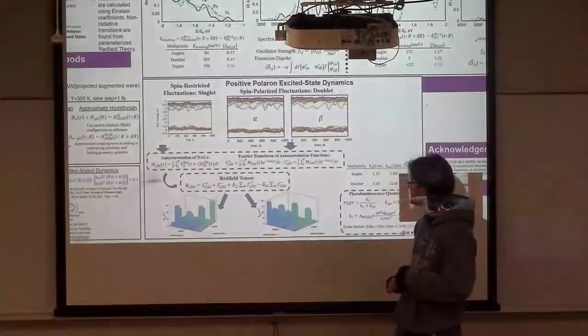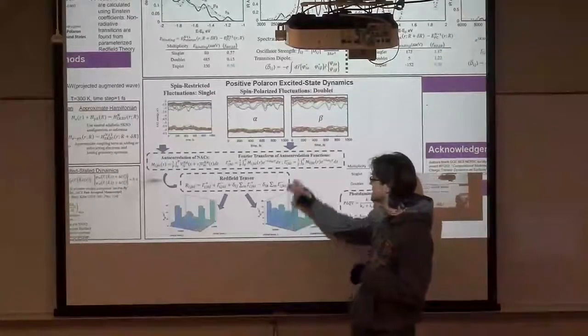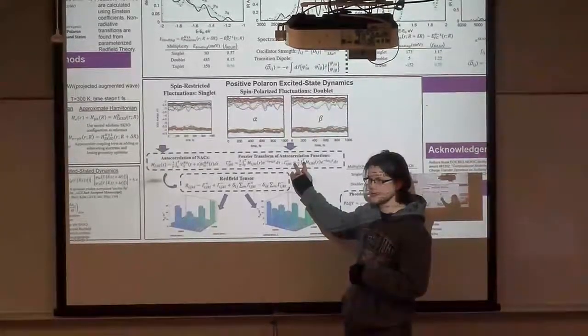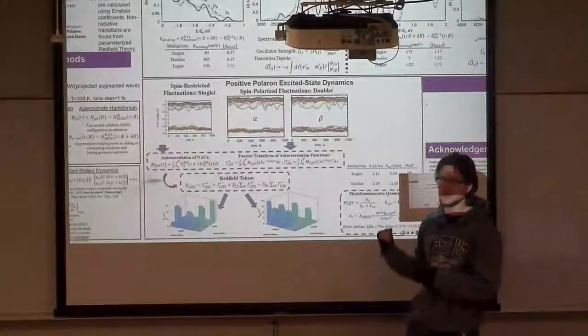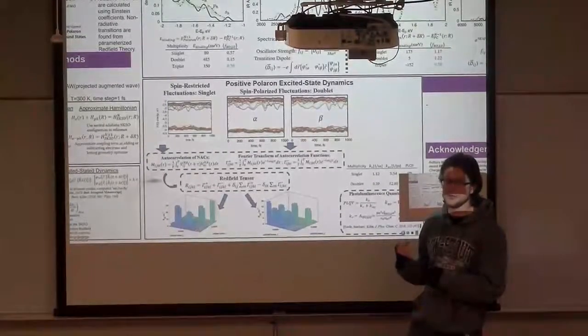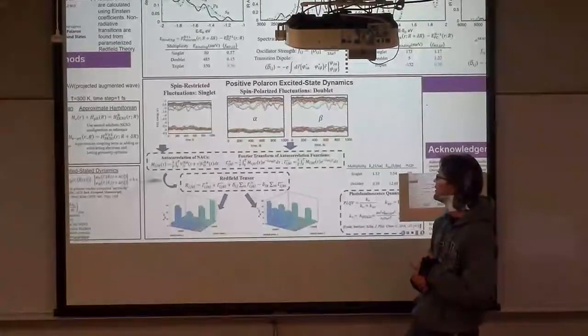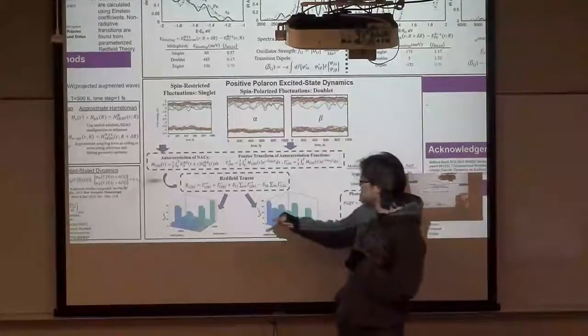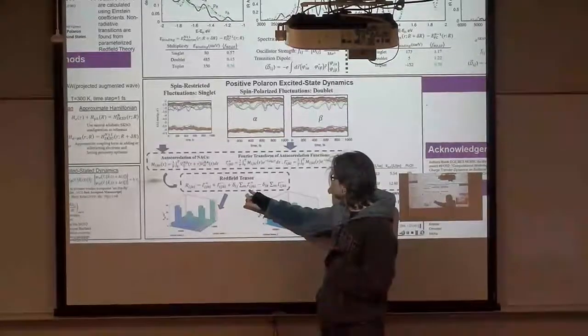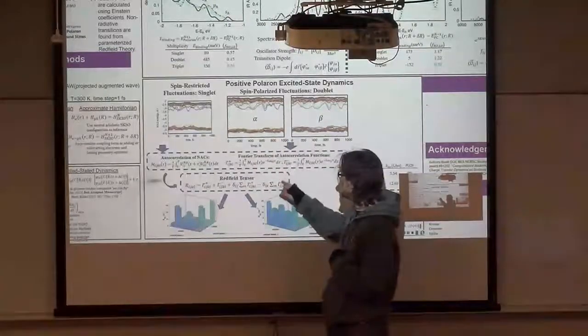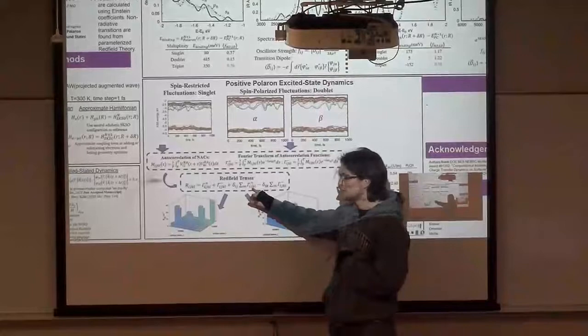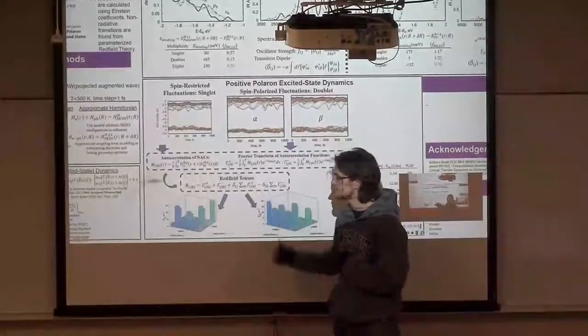If you take the Fourier transform of those, you extract out the phonon modes that couple to those degrees of freedom. So you essentially get your spectral density, and using those rate equations, we can parameterize the Redfield equations, which describe dissipative transitions.